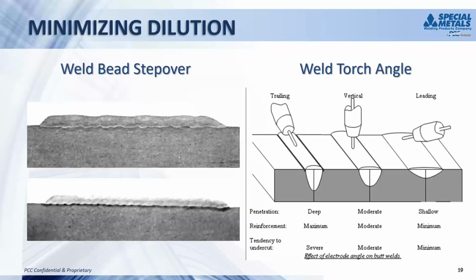Next slide. Some tricks to minimize dilution. Weld bead step over when you're doing cladding is probably the biggest and best trick. If you can imagine, the closer you put the weld beads together, the more you're actually burning into the previous weld bead and not the base metal. So you can minimize the dilution and burn less of the base metal.